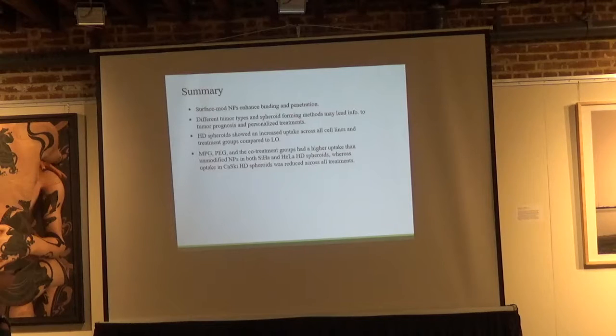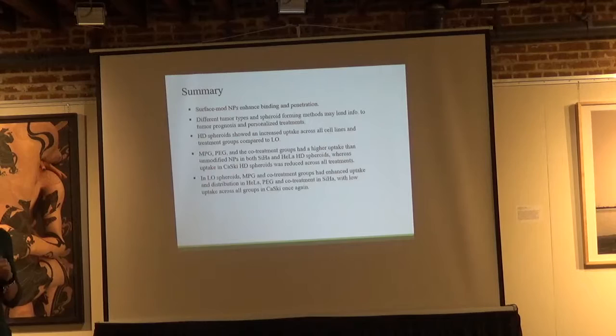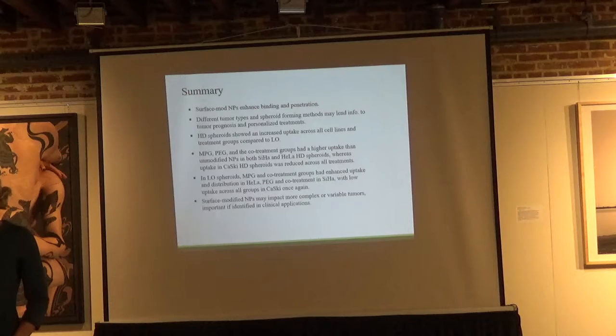that's relative to the larger liquid overlay spheroids, overall the MPG, PEG, and co-treatment models provided higher uptake. The same thing in liquid overlay spheroids. While they had overall lower uptake, the trends were pretty much the same. And so our hope is that surface-modified nanoparticles may impact more complex or variable tumors, which would be really important in clinical applications if they had the ability to either genotype or phenotype some of the patient tumors and understand their cell origin.